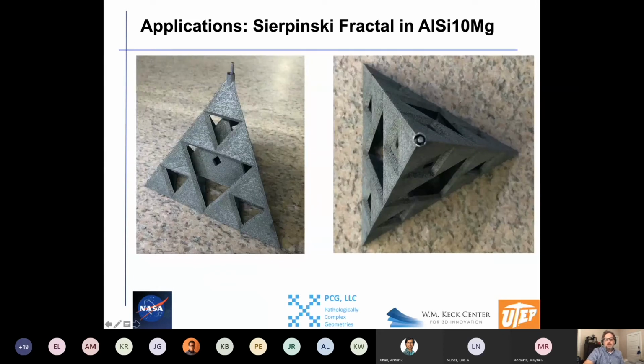And this is an antenna, and we're actually starting a company over this. This is a ship in the bottle. This is a pyramid, and it's a fractal. What that means is this triangle has 3 triangles in it, and that triangle has 3 triangles in it, and it's sort of self-replicating. I don't know, it's a geometry thing. And it's got this triangle inside of it that's a ground plane, and this is the irradiating element. And right here, you can put a coaxial cable on that, and you can use this as an antenna. It's very broadband because it's a fractal, and it would fit in a UAV nose cone. We're about to potentially write a proposal to put it into little CubeSats, satellites that are pretty small.